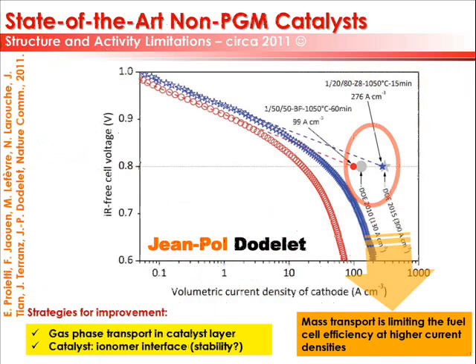away. And people usually try not to publish low loadings of electrocatalyst research because at low loadings peroxide flies out. They always want, the best graduate student or a postdoc tries to put as much catalyst as possible on the electrode, then all the peroxide is internally consumed, and he says, boss, I made the 4-electron reduction catalyst. Voila. This is the biggest lie. And this lie propagates through papers from Electrochimica Acta to Science and Nature.